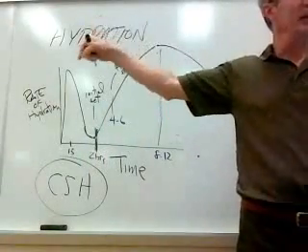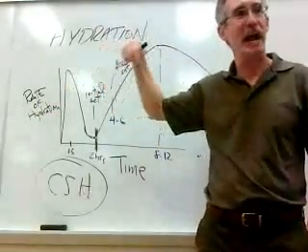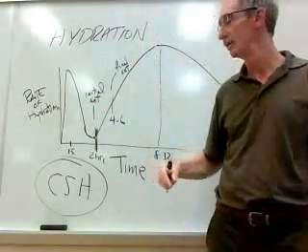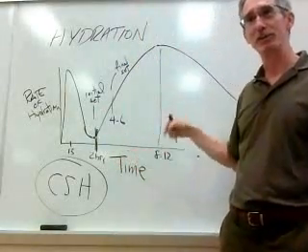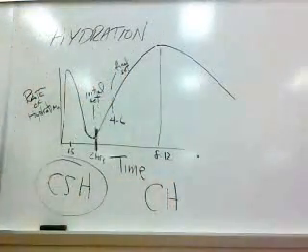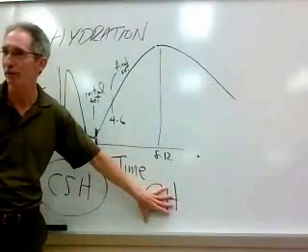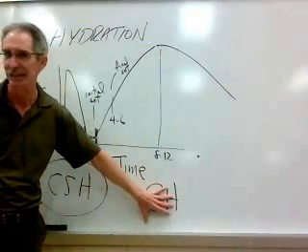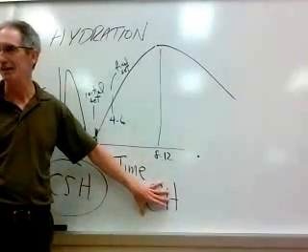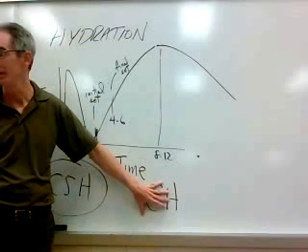And we talked about the pozzolanic material. We said how it reacts with something later on to actually help us out. What it reacts with is this calcium hydroxide that's formed too. About 50% of the crystals are CSH, about 25% of the crystals are calcium hydroxide, or 30%. This is the really good stuff. This stuff, not so good. All right, and it can cause us problems later on too.